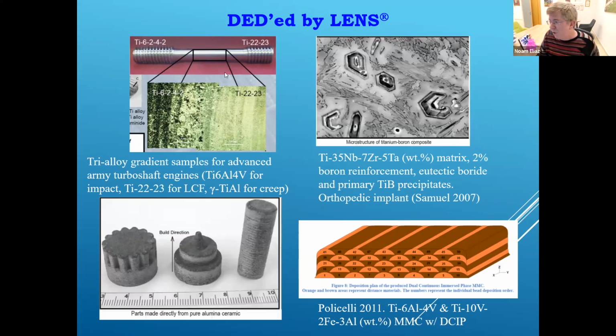It's quite impressive. On the left top side, you can see functionally graded materials where you actually have, in the whole project, not in this specific picture, three alloys: titanium 64 that gives you high resistance for creep, titanium 2223 for low cycle fatigue, and the gamma titanium aluminide intermetallic for creep resistance. So you can now combine different materials in one part to get, in this case, optimized mechanical properties, okay? So this is titanium 22 aluminum 23 niobium.